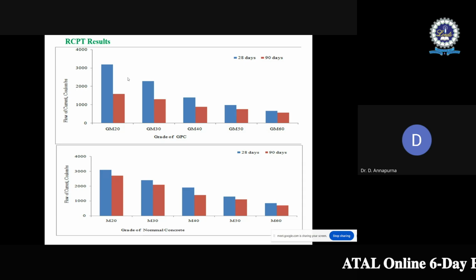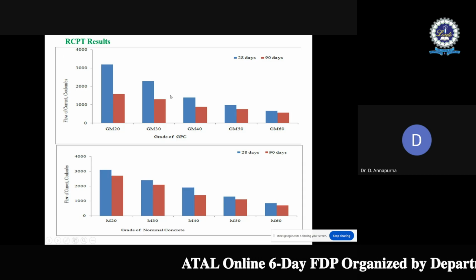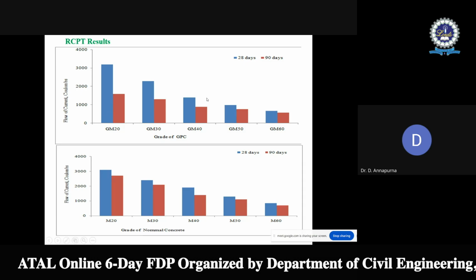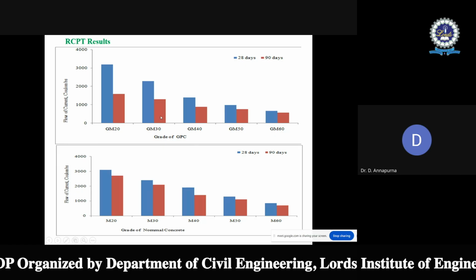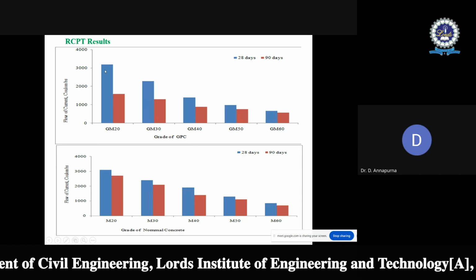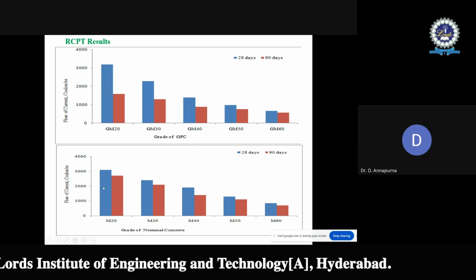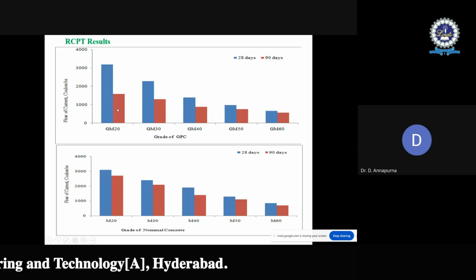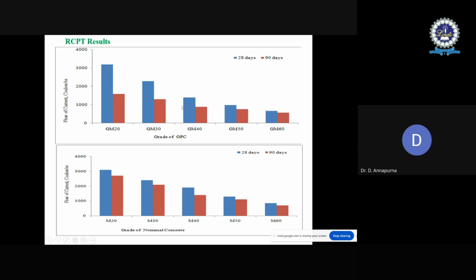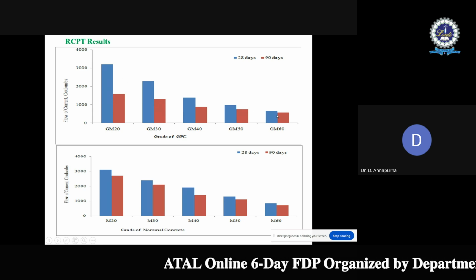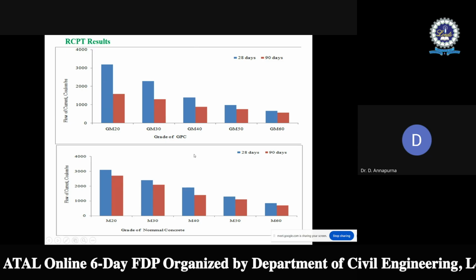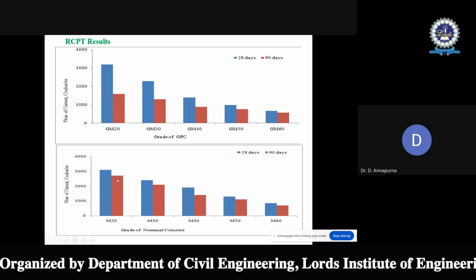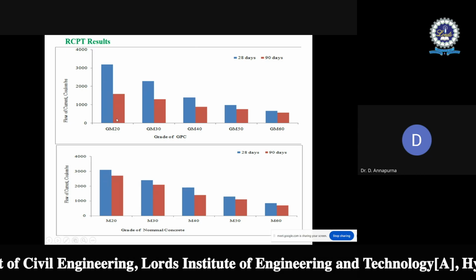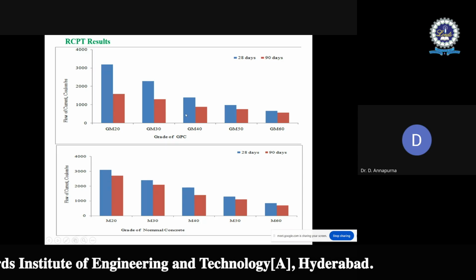From these results, it can be observed that chloride permeability decreases as the curing age and the grade of GPC increase. If we look at the grades of GPC between 28 days and 90 days, as the curing age increases, the chloride permeation decreases, and as the grade increases, chloride permeation also decreases. When compared with normal concrete, similar behavior is observed between geopolymer concrete and normal concrete.